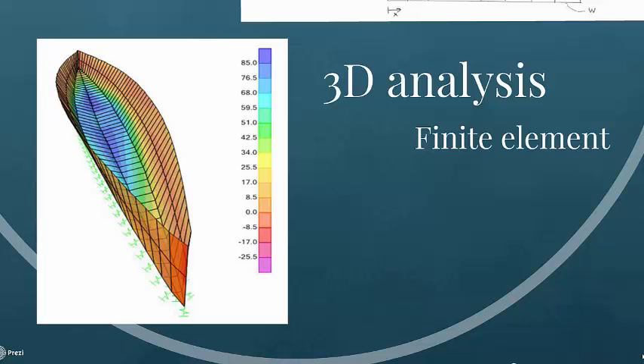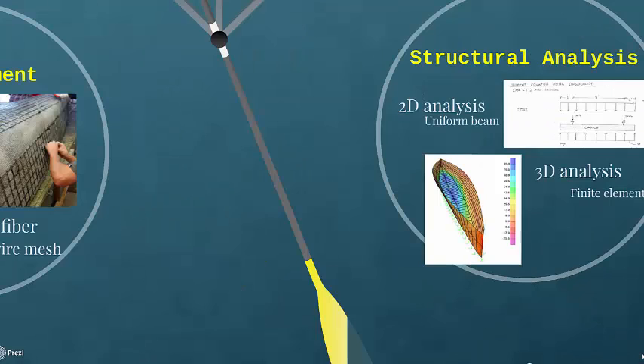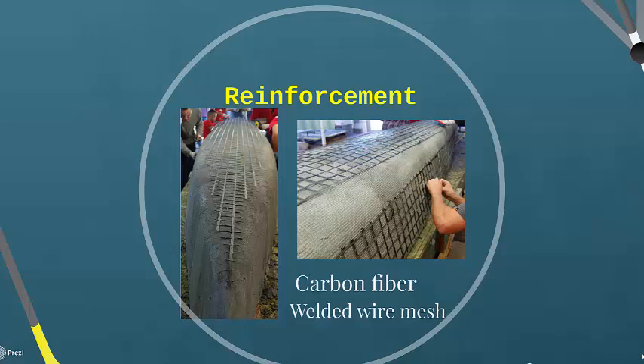Also, the mass density of the concrete and the weight of the paddlers were entered into the computer program SAP 2000 to complete the load case. The results were quite similar to that of the hand calculations, with a maximum tensile stress of 85 psi located under where the paddlers sit. The reinforcement options used were a carbon fiber mesh and a 23-gauge quarter-inch welded wire mesh.